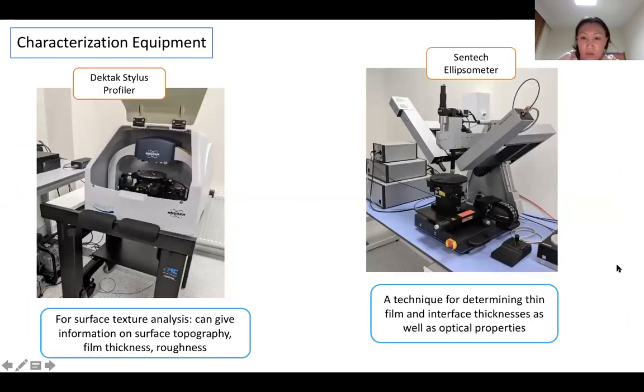Next, we have two more tools, located in room 255 on the second floor. First is the Dektak stylus profiler. It has a diamond stylus with only a 1 micron radius, and it gives you a profile of the roughness of your sample. People usually use it to define the thickness of the material. Then the ellipsometer. The ellipsometer is used for dielectrics, oxides, for example, silicon dioxide, zinc oxide, to define their thickness and optical properties.